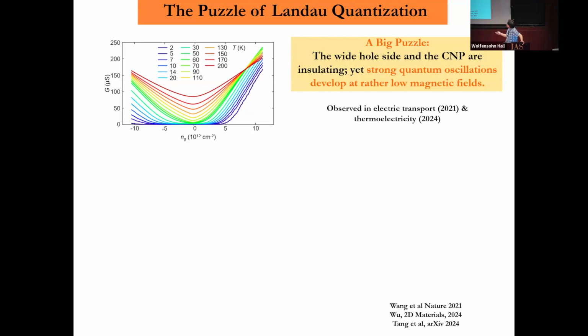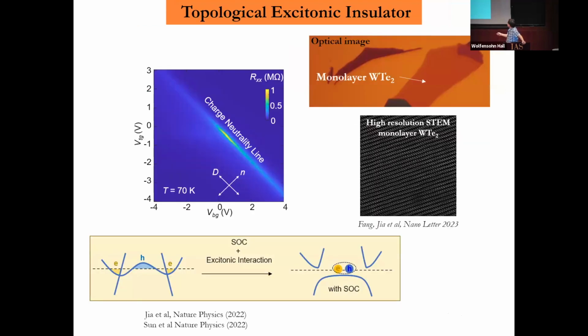One thing is, if you try to dope a lot of electrons or holes, especially on the hole side, you do not really get a metallic state. There's a wide range of doping where you have insulating states on the hole side. And accompanying this excitonic pairing, as you already saw from Nong's talk, is that applying an electric field can flatten the band. In this case, the excitonic pairing interaction drives very different electron and hole states.